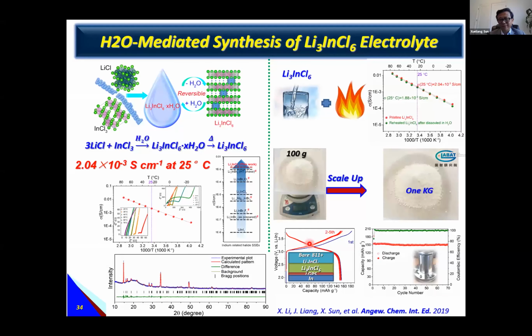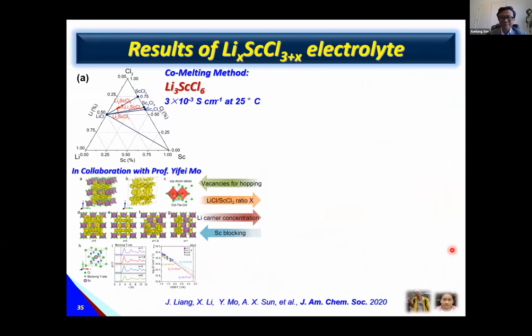We also demonstrated the battery, still using this layer with the anode, and the battery can show stable performance. Recently, we also work on other systems. For example, here, lithium scandium chloride also gets 10 to the minus 3. Also thanks to the collaboration from Professor Yifei's group. We try to understand the mechanism to see why they have very high ionic conductivity. For example, the vacancy, the hopping and the concentration, the barrier, and also the scandium blocking are all factors here.